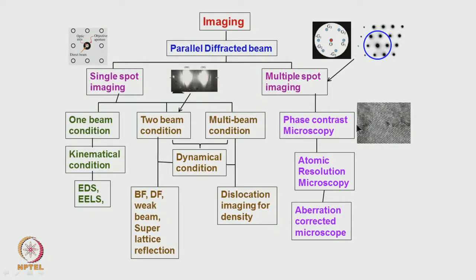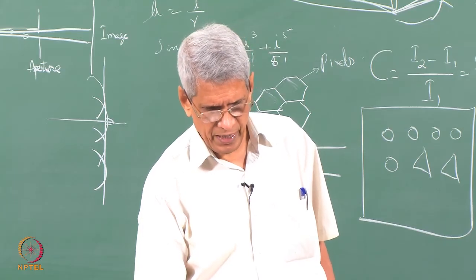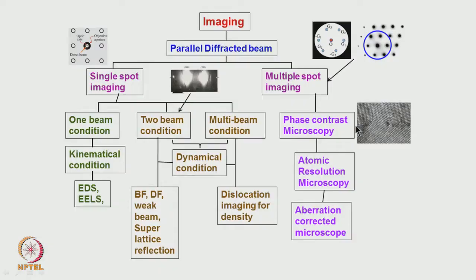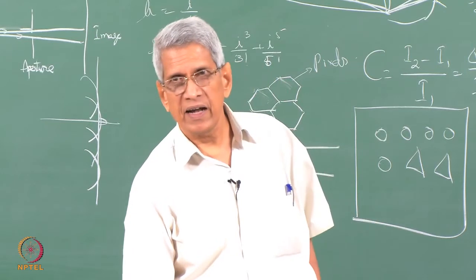And if we can make the lens aberrations almost zero or less, and in phase contrast microscopy there is a way to correct for that aberration, make the aberration minimum so that we see this sort of pattern. And when the spherical aberration is made very small, those microscopes are aberration corrected microscopes, and they give atomic resolution microscopy. There is another type which I mentioned right when we started in the last class, that is called STEM.